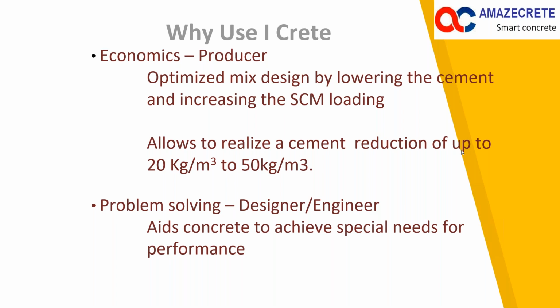For example, somebody is using 40% OPC and 50% GGBS. We can go down to 40% OPC and 60% GGBS, or 35% OPC and 65% GGBS, and use iCrete. So in fact, the more the SCM, the better is the performance with iCrete. So it helps to reduce the cementitious content.